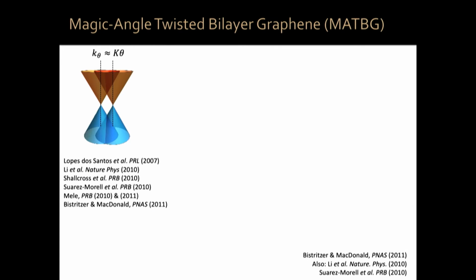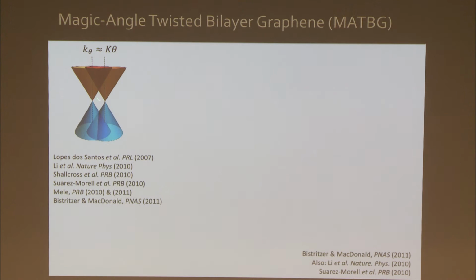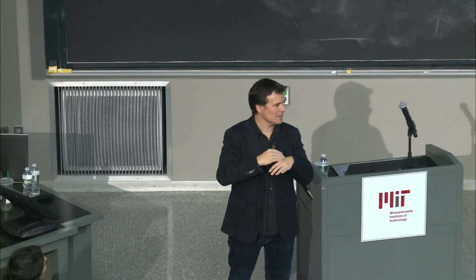So let's imagine we have already two graphene sheets on top of each other, and there's a small twist angle between the two graphene sheets. Okay? Now, the electrons in the two graphene sheets, in layer 1 and layer 2, have this energy momentum dispersion. Okay? And the separation between those Dirac cones is proportional to that small twist angle. This would be the situation that would be realized if electrons in one graphene sheet did not know that the other graphene sheet exists.